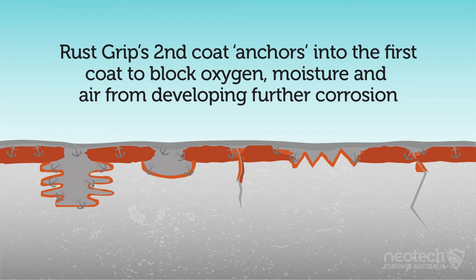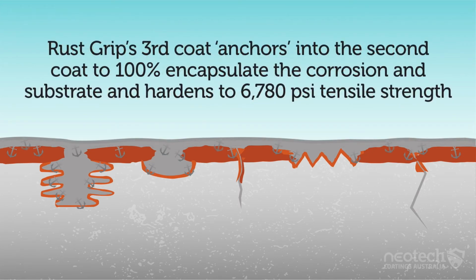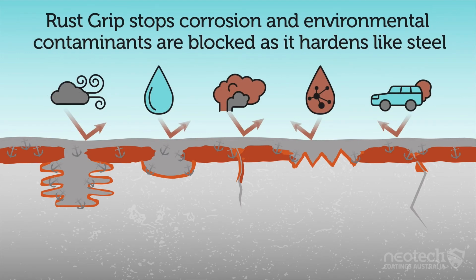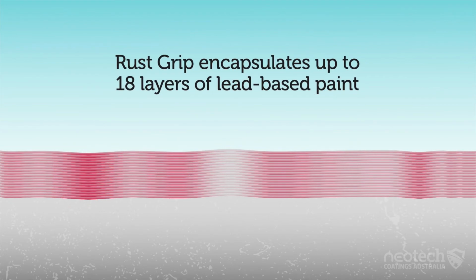The second coat of Rust Grip continues to fill in pinholes and any gaps missed and anchors to the first coat to completely block oxygen and moisture developing corrosion. The third coat anchors to the second and 100% encapsulates the corrosion and metal and hardens to 6,780 psi surface tensile strength, unlike any other coating. Rust Grip then stops corrosion dead in its tracks, keeps moisture and environmental contaminants out, and hardens like steel with over 20 years protection. Rust Grip also is tested and rated to encapsulate lead-based paint.